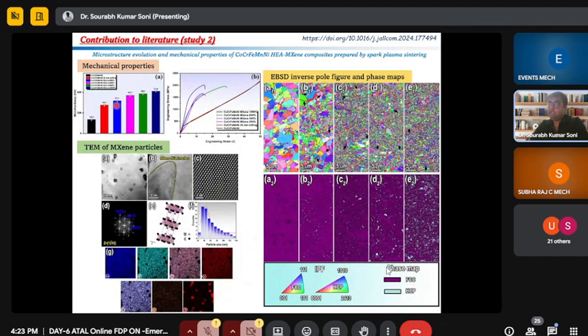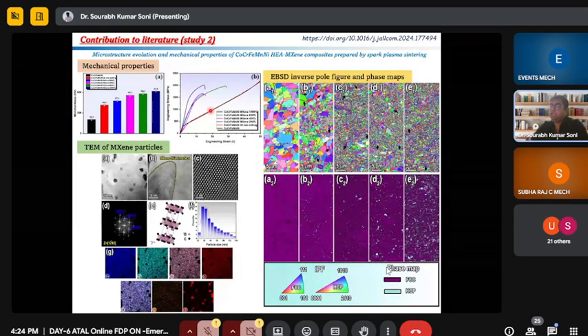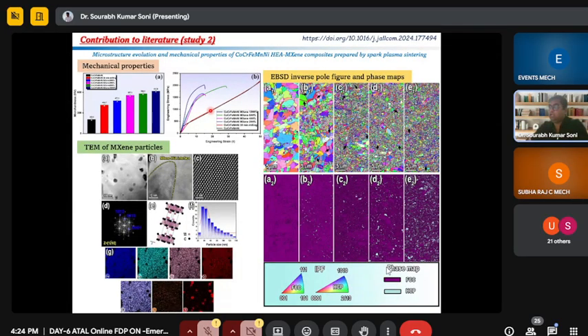And this is the microhardness. So we are observing the increasing hardness with the improvement in the reinforcement particle. This is the engineering stress curve. In this, I want to highlight that nowadays, if you mix the reinforcement material, we will easily achieve a higher UTS, but ductility is reducing.